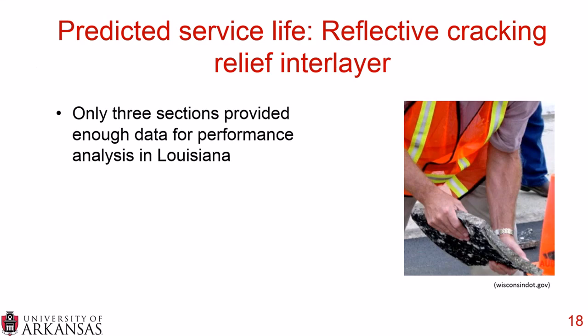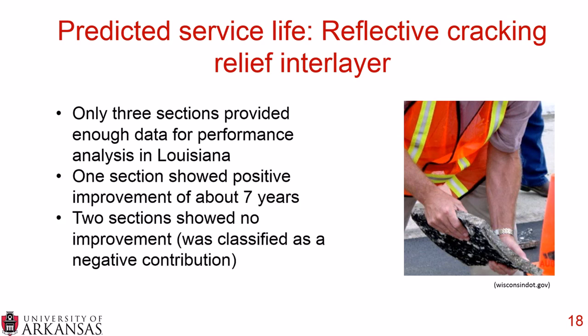And then finally, they looked at 3 sections of reflective cracking relief interlayers, and they showed that one section showed a positive improvement of about 7 years, and 2 sections showed no improvement. And in the report, they actually classified this as a negative contribution because, of course, it costs a little more money. And if there's no improvement, then it's not a positive contribution.